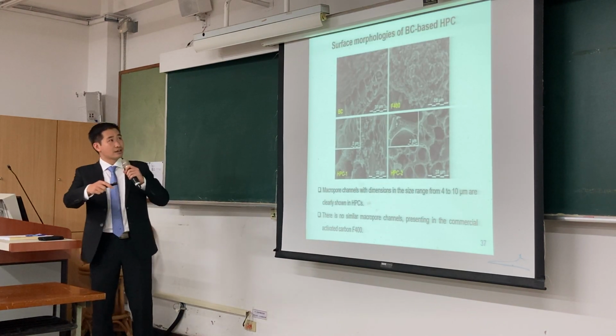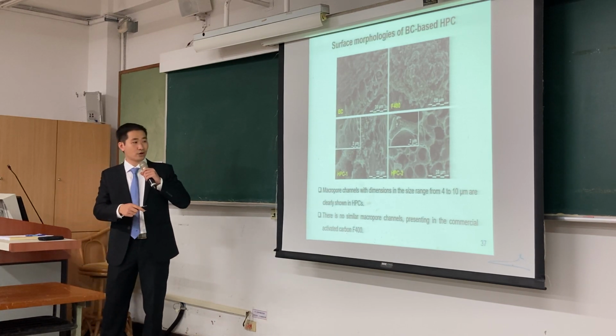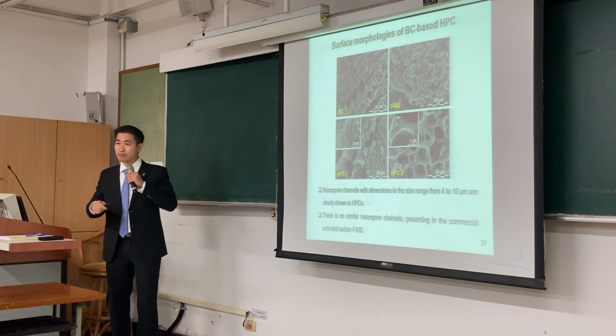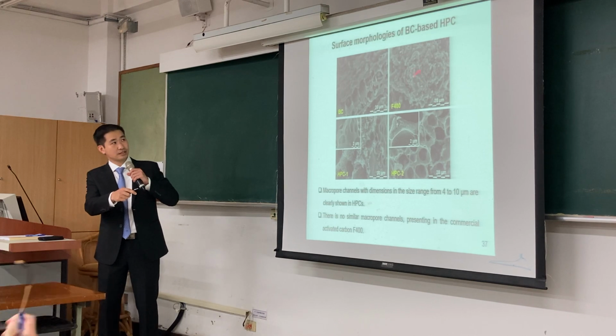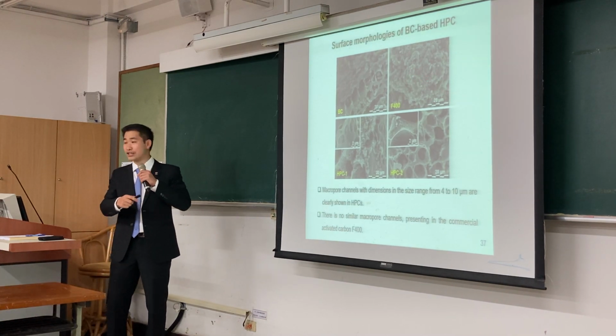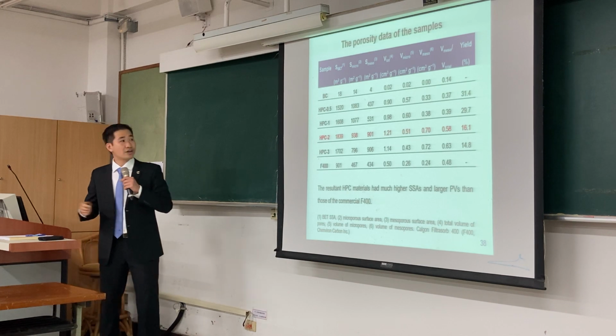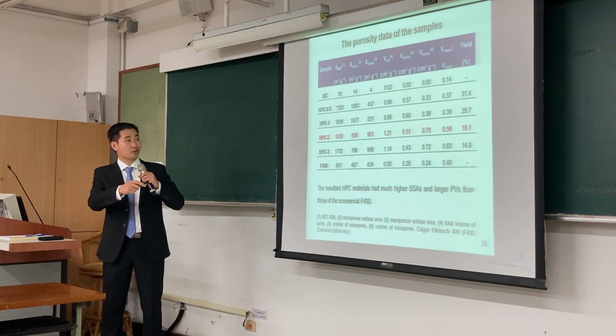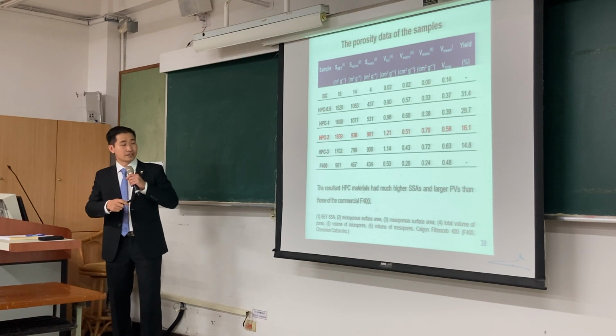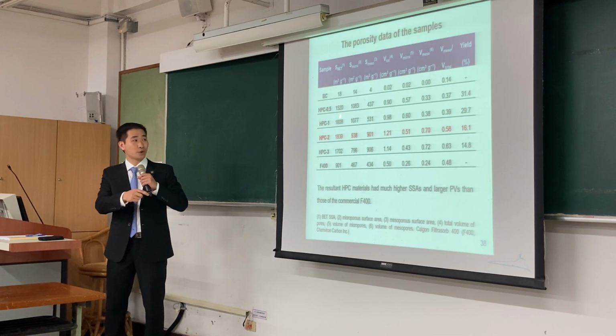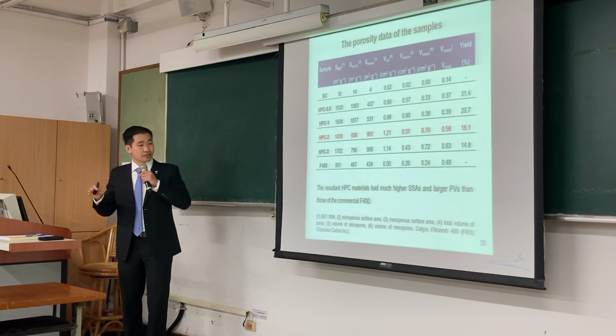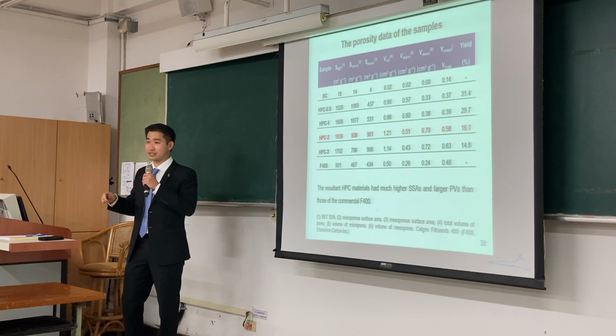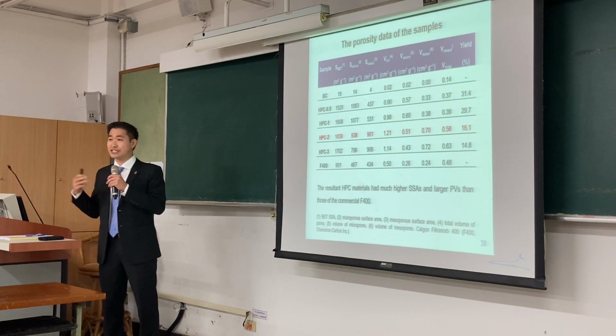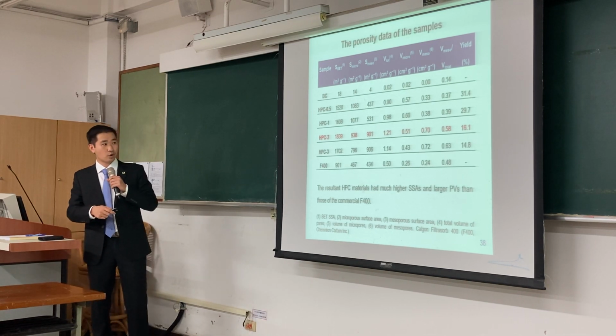We can see that macropores can be observed in the HPC material. However, no similar macropores can be seen in the commercial material F400. More interestingly, we can see when the activation time increased from 0.5 to 2 hours, the specific surface area increased. However, when the time increased to 3 hours, the specific surface area decreased. This decrease may be due to the collapse of the carbon framework.